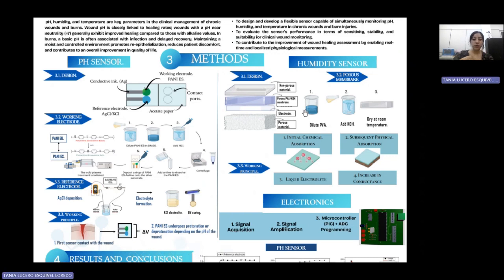Now for the humidity sensor, we dilute polyvinyl alcohol into deionized water, and then we add a potassium hydroxide solution and let it dry at room temperature for some days. And this forms a porous membrane sensitive to humidity. As you can see in the design, the middle part is the porous membrane made from PVA and KOH.